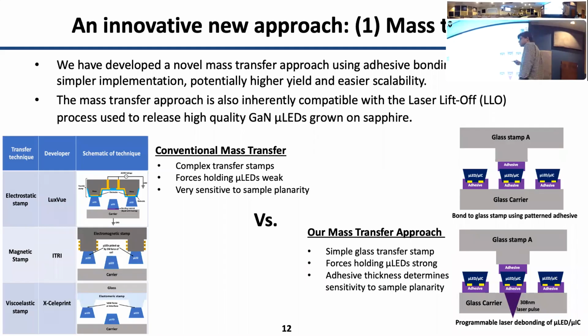Yeah, so should I explain later? The mass transfer process is more universal. We can use this technique to assemble devices on any substrate. So we could assemble it on a silicon backplane or even a PCB backplane. Because in the adhesive bonding approach, the only processes involved are die to wafer or wafer to wafer bonding and laser debonding, and those techniques are already available in most packaging centers.